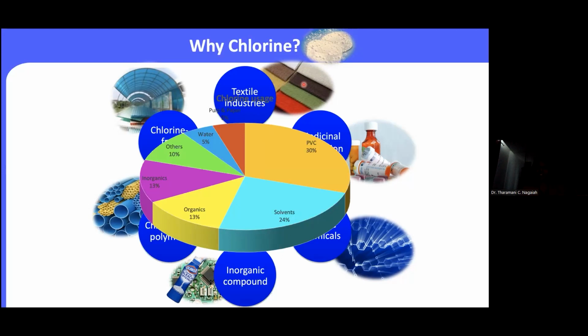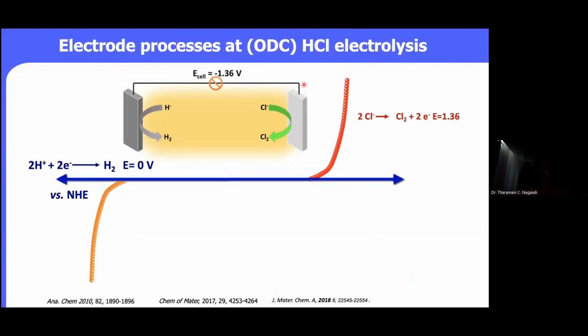However, the byproduct which is produced is HCl. And we do not know how to utilize this HCl, and it is not eco-friendly at all. The developing countries are simply quenching with lime, which is not an eco-friendly process. Some industries do HCl electrolysis, but the major problem of this HCl electrolysis is the 1.36 V, which means an energy-intensive process, because the chlorine oxidation takes place at 1.36 and the hydrogen at 0 volt. That means 1.36 V is required for this.